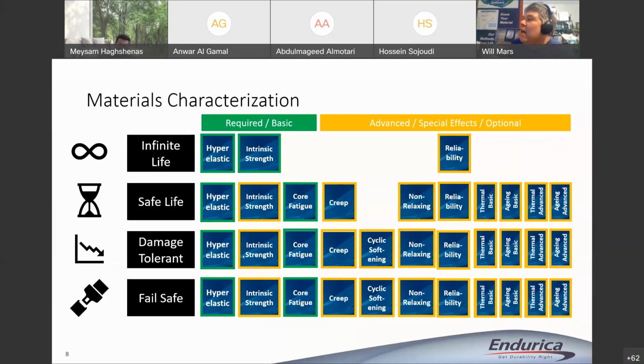If we're going to do damage tolerant, now maybe we have to take into account the cyclic softening, because the material is going to get softer, which means I have to recompute my stresses and strains on some kind of incremental basis, right? Every 100,000 cycles, I have to update my model to reflect the fact that the stress strain curves have become softer. And yeah, so you can sort of see how these different characterizations get more complicated and scale up as you adopt more and more sophistication into your analysis.